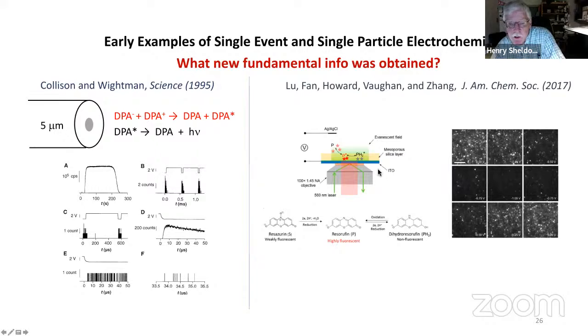to get out information. This is an example recently from Bo Zhang's lab at the University of Washington, where they have a transparent electrode and they shine light up through it, and they excite molecules that are adsorbed on the surface as a function of the electrode potential. And the molecule they're using here, if you reduce this guy, it goes from a non-fluorescing or weakly fluorescing molecule to one that's highly fluorescent.